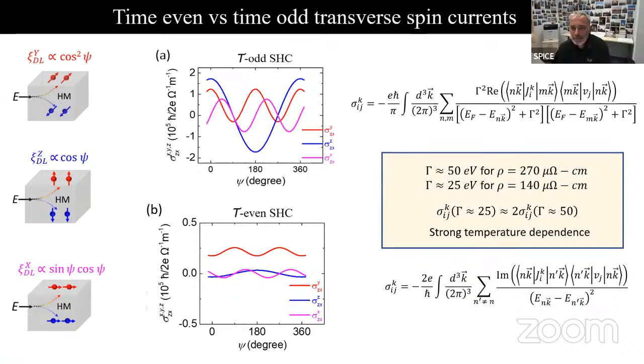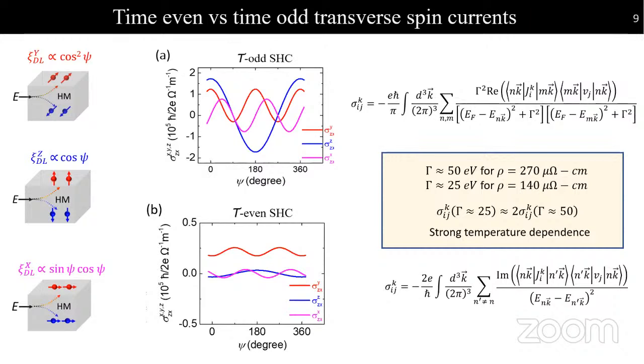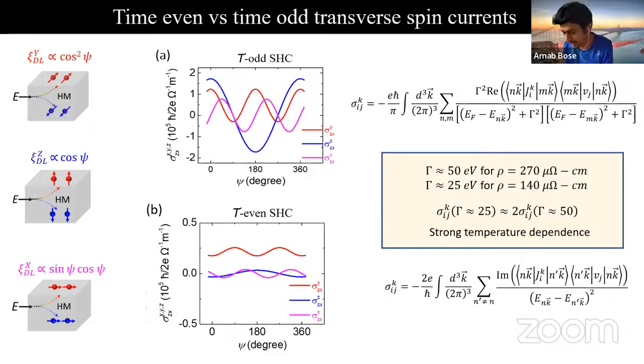Go ahead. Thank you, Arnab, for the amazing talk. It would be helpful for me if you could explain what exactly are these time odd and time even spin currents. So you can think about time odd spin current in this manner. Suppose you have a magnet, if you run any charge current in the magnet, you get the spin polarized current. And if you flip the magnetization, you get the opposite sign of spin current, meaning you can control the sign of the spin current by doing the time reversal operation. So that is possible in ruthenium dioxide, and that effect is very strong.